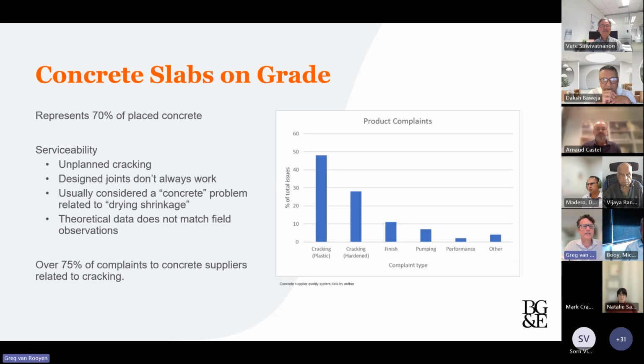So slabs on grade probably still make up, well, we think about 70% of the concrete placed, and really come down to problems with unplanned cracking. I think there was a little chat earlier about planned cracking being good cracking and unplanned cracking being bad cracking. And so the joints don't always work. And we relate this to a concrete problem and drying shrinkage.